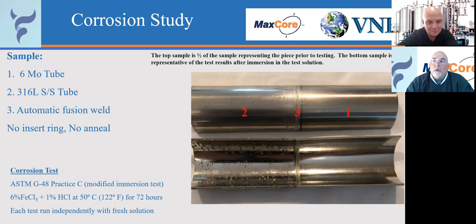This shows a couple of things. First off, it shows that the 316L is certainly more susceptible to corrosion. You can see pitting all over the surface of that 316L. But one of the questions that always comes up is, do I have to over alloy that weld when I'm putting that type of joint together? And secondly, can I make that type of joint? Well, yes, you can make the type of joint.